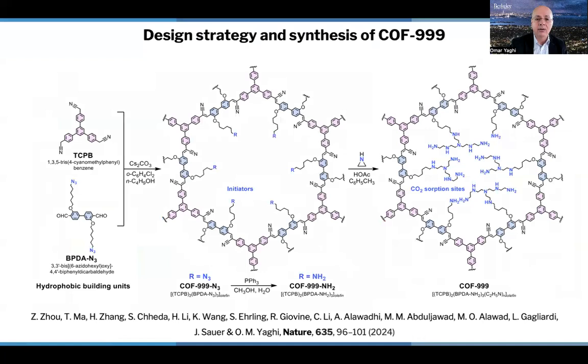This is the kind of stability that made us really excited about addressing a challenging problem such as CO2 capture from air. And accordingly, we took that chemistry and, without describing the details of it, attached polymeric amine units onto the backbone of that COF. You can see here the amines in blue. And for each amine, you're going to be able to capture a CO2 molecule. And without these amines, you cannot capture CO2 from air. So these are needed. The material I showed you is stable under varying severe conditions in acid and base and corrosive media.